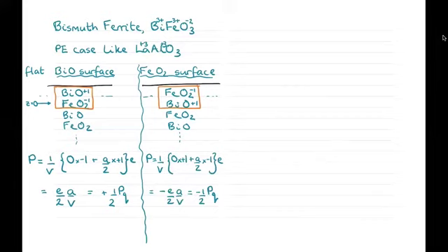And again, we see that both of these fall on a centrosymmetric polarization lattice, which is allowed to have values of the half quantum plus or minus n times the polarization quantum. And to get other values, we would have to create non-smooth, non-flat surfaces. Then we would get answers, for example, like plus 3/2 times the polarization quantum and so on.